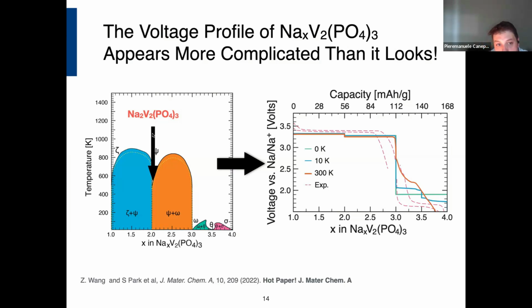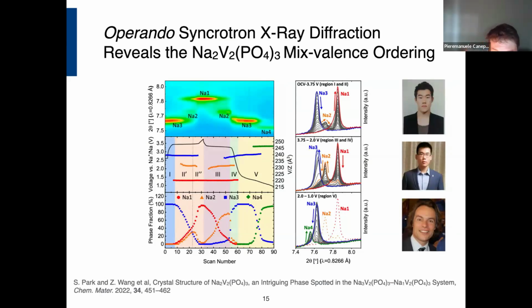And indeed, they went to the lab and they were able to form this line compound material. Long story short, when you take this line compound material and start extracting sodium from 2 to an inferior quantity of x and then try to reintercalate sodium, sorry, I wanted to say that they now see the sodium 2 phase. These are operando synchrotron XRD measurements done by my colleagues Christian and Sun Q Park. You can see that as you cycle the battery, you see a strong signature of sodium 3 and 1 sodium per formula unit appearing, but there is also a signature of the existence of sodium 2, the line compound that we observed computationally.